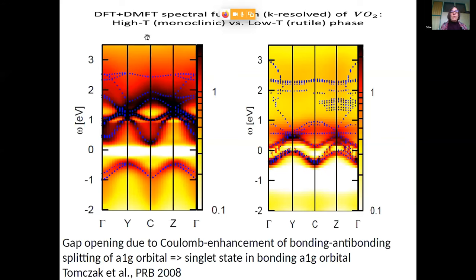On the left-hand side, you see the K-resolved spectrum of the insulating phase. On the right-hand side, of the metallic phase, of the rutile phase. And the first striking feature is certainly that in the rutile phase, in the metallic phase, you have much less well-defined features. And very rapidly, as soon as you are here, relatively small energies from the Fermi level, you have quite broad features, which indicate that lifetime effects are really important here. And that means that many-body correlations actually report corrections to the band picture in this metallic phase.